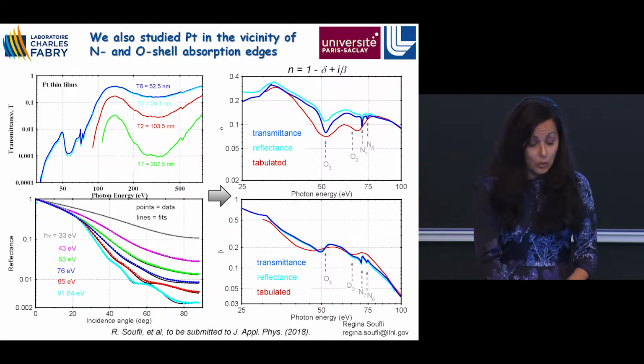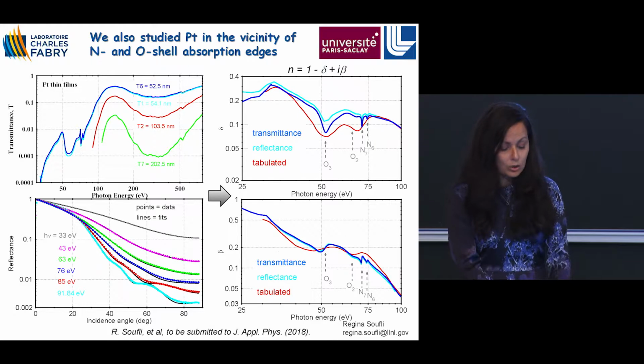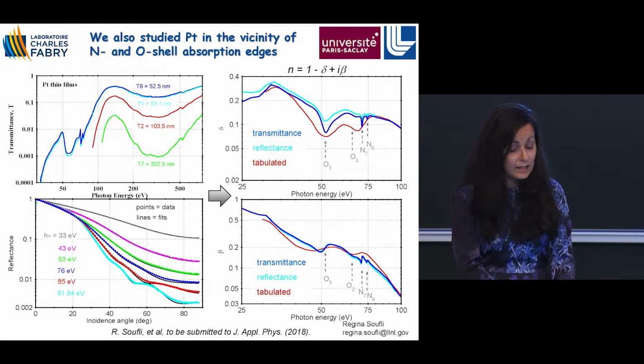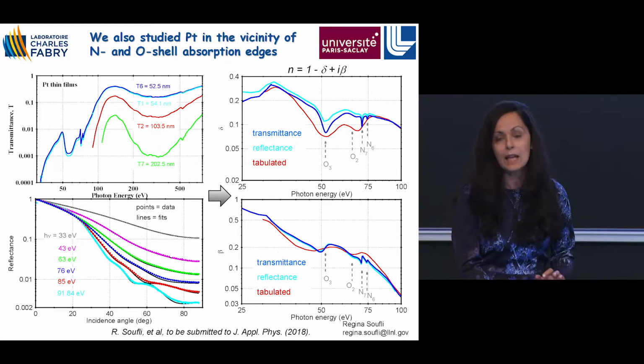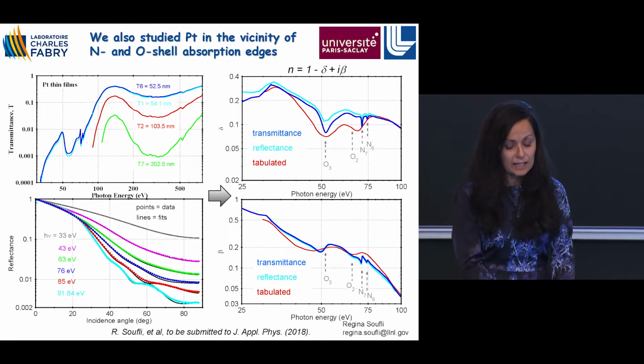Okay. So we also, just to show you that this is ongoing work, we very recently studied the refractive index of platinum in the vicinity of the N and O shell absorption edges. We used again transmission measurements and also reflectivity measurements, reflectivity versus incidence angle for a few photon energies in the low part of the spectrum here. And when you do reflectance measurements, you can fit both delta and beta directly from the reflectance data.